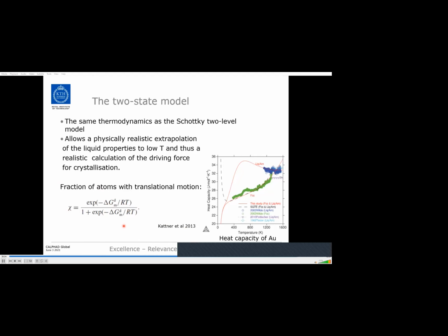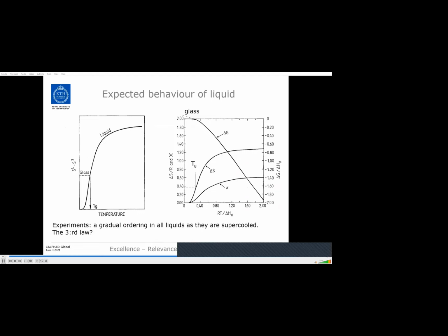And here is an example now for pure gold. It shows the heat capacity in the FCC phase, and here in the liquid, which is undercooled. Here the symbols are experimental, and here is the behavior predicted by the model. So we expect that the entropy of the liquid will decrease until slow kinetics put an end to it and we reach a glass transition. And here are the corresponding variations in the Gibbs energy and the entropy. And here is the fraction of atoms having the translational motion. And you can see that close to the melting point it may be around 0.5 or something.